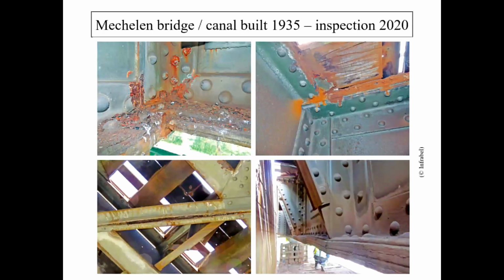In early 2020, the owner of the railway infrastructures in Belgium ordered a thorough inspection of that bridge, which had not been maintained and painted for at least 40 years. A thorough inspection beyond routine inspection. Elements of the decks were found to be significantly corroded by rust, and there were also signs of the damages here resulting from the blasting of 1940. But the corrosion problems can be fixed with an overhaul of the deck.